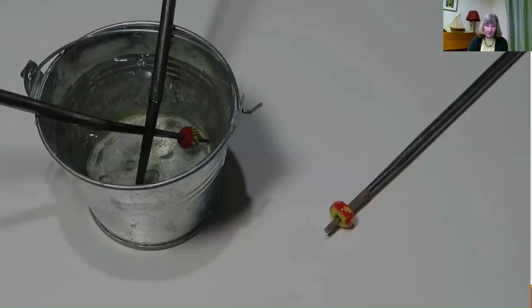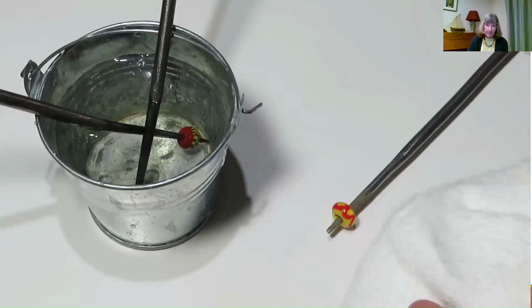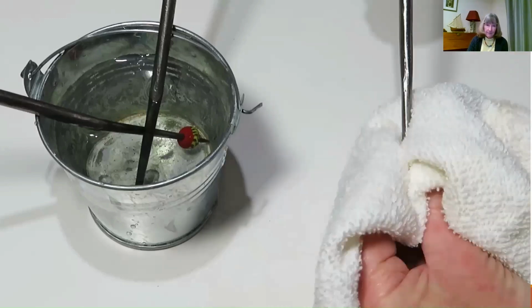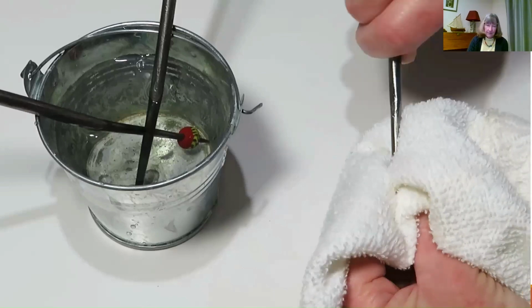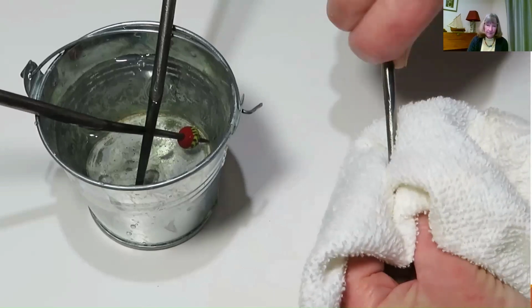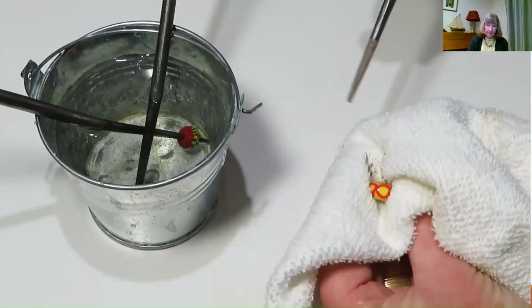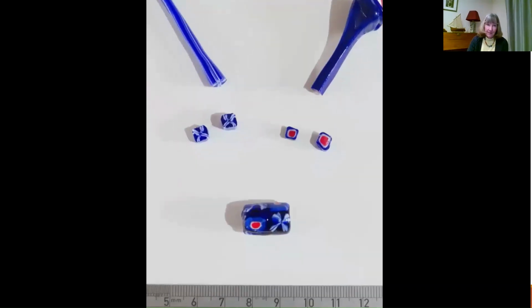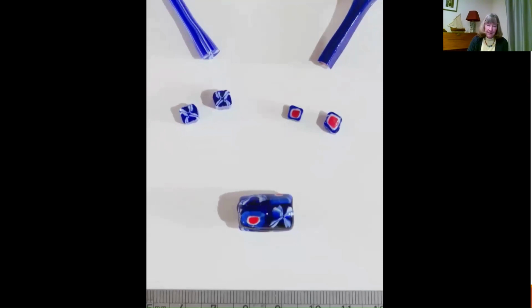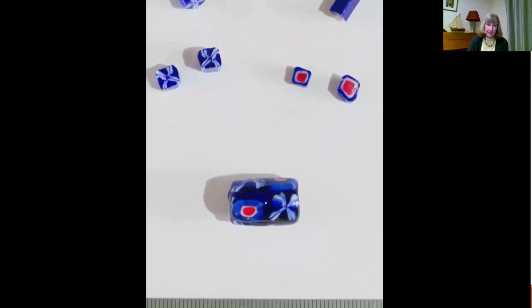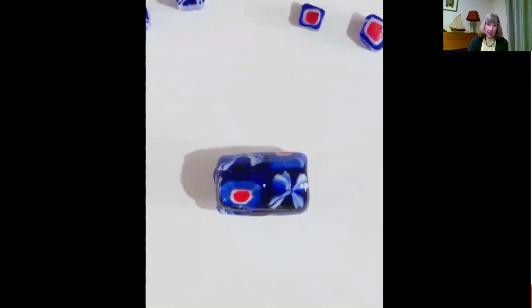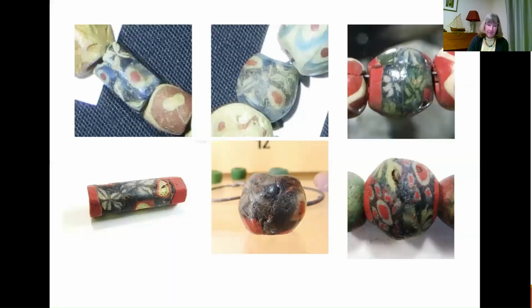Once the beads have been cooled, they are soaked on the end of the mandrels in water to soften the clay slip. And then, with a bit of effort, the mandrel is removed, and there is the finished bead. Mosaic beads are some of the most difficult to replicate. Slices from pre-made millefiori canes are applied to a mandrel and melted to make beads. These beads are found in small numbers across Europe, and their distinctive patterns give clues to the workshops they were made in.